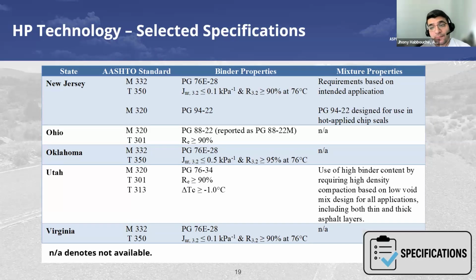But Utah doesn't stop here. You can achieve that binder with about 5% polymer, not necessarily the 6 and the 7 like Virginia. Virginia, for you to achieve that binder, you need at least 7, 7.5 polymer. Utah has more of a requirement on the mixture, so it's more of a system for Utah compared to just a binder swap for Virginia.